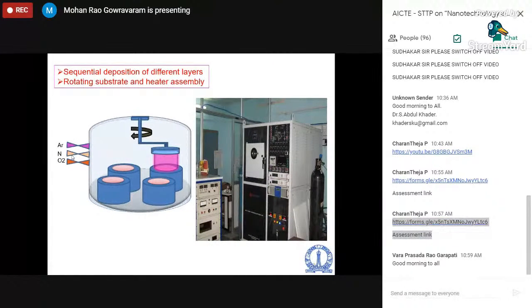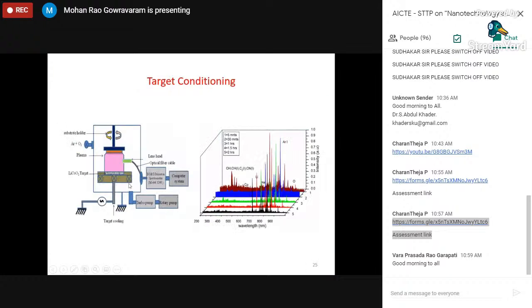depositing lipon, because if you take a lithium phosphate target, Li3PO4, and put it in nitrogen plasma, some nitrogen replaces oxygen. And oxygen is also introduced during deposition of lithium cobalt oxide, because when you are sputtering lithium cobalt oxide, there is a possibility of dissociation of some oxygen, so that has to be replenished by this external oxygen.